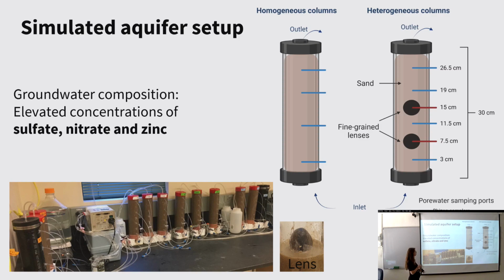And here we focused on the behaviour of the heavy metal zinc that was introduced into the groundwater on day 21 of the experiment, which was continued for a total of 77 days. We monitored the pore water chemistry on a weekly basis through sampling ports located throughout the columns, and we also destructively sampled them at the end of the experiment for solid phase analysis. And here you can just see how this experimental setup actually looked, and here is when we embedded that fine-grained lens into the sand.